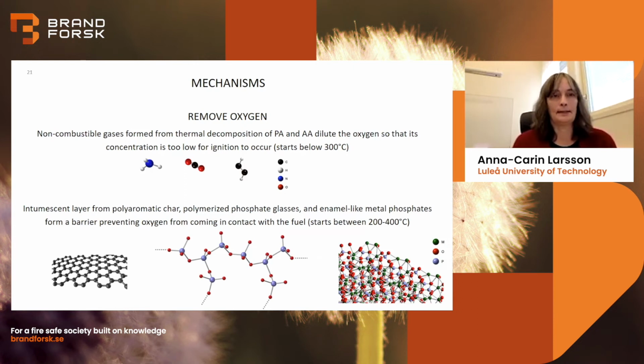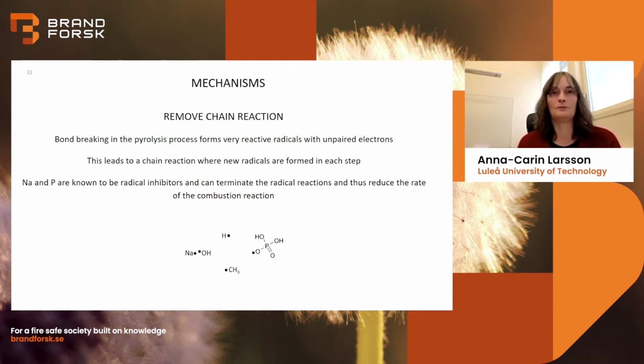And this intumescent layer that is formed, the polymerized phosphate, which is a kind of glassy material, and the third component, the metal phosphates that form, which are enamel-like, calcium phosphate is the same mineral as we have in our teeth enamel. So all those will form a barrier that will also prevent the oxygen from coming in contact with the fuel. And this happens also between 200 and 400 degrees. So all of those mechanisms are relevant before the natural thermal degrading temperature of cellulose.